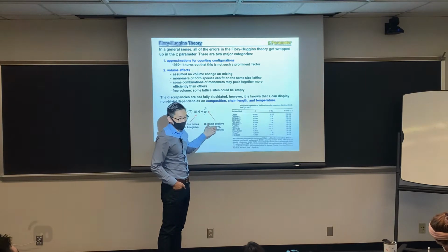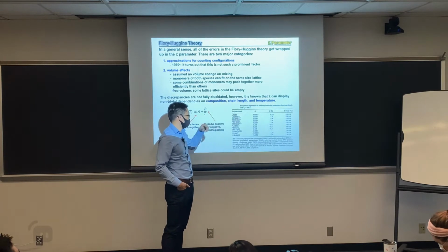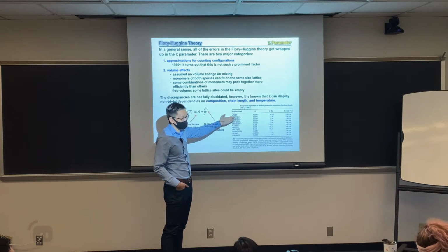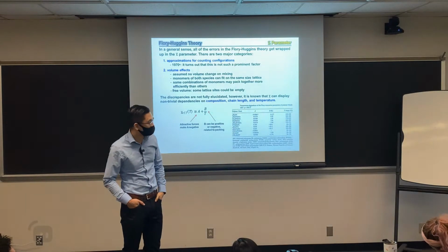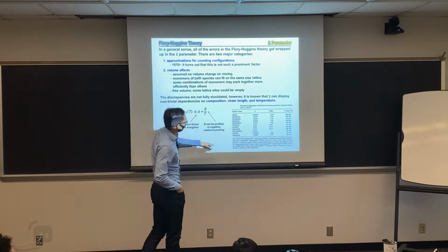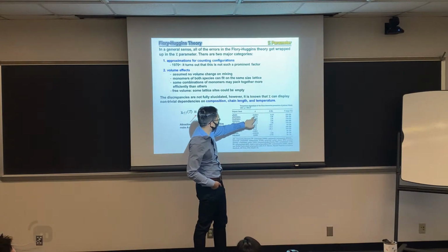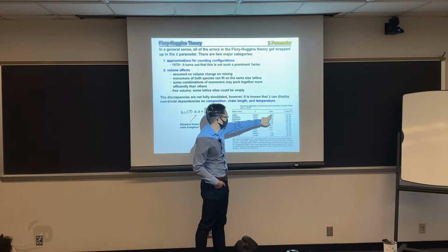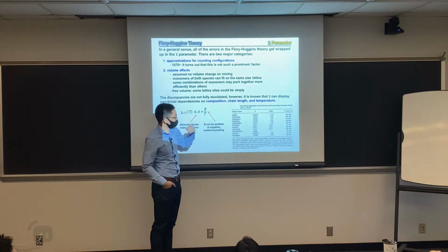In this scenario, we also see what the DPS means. D means deuterated, okay? When you're doing neutron scattering, you will see people do deuteration. One of the effects of deuteration is that it changes the scattering length density. It changes contrast. But you will see that deuterated PS and normal hydrogenated PS have a very low chi parameter. A is low, B is a relatively high value. But if the molecular weight is high enough, you can still have phase separation.